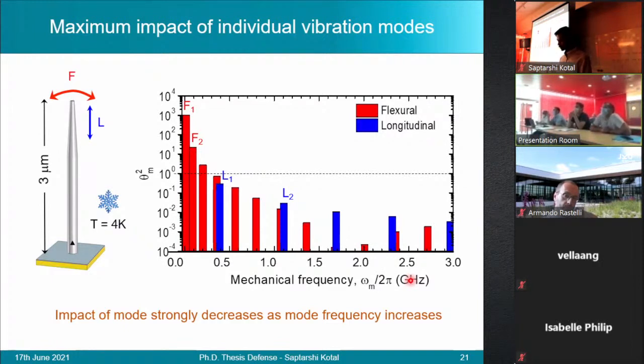Therefore, from the finite element calculations that were performed, here I represent theta m squared as a function of the mode frequency for the first few modes up to a frequency of 3 gigahertz. As we can see, the impact of each mode progressively decreases as their frequency continues to increase.